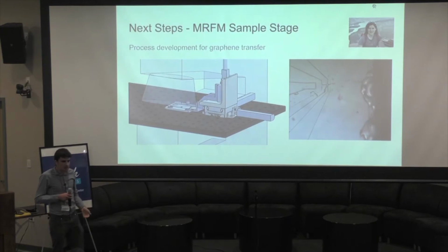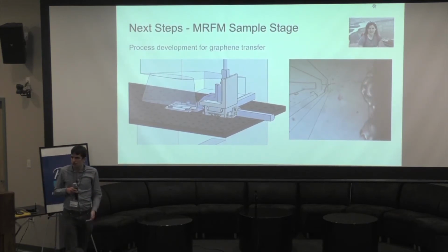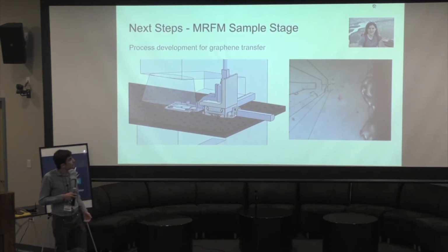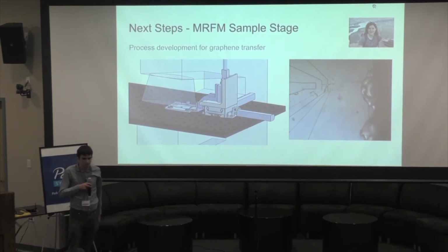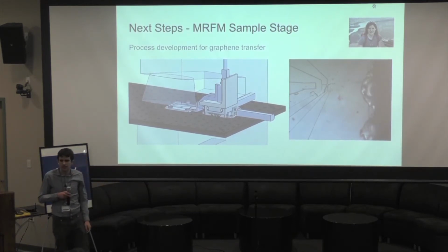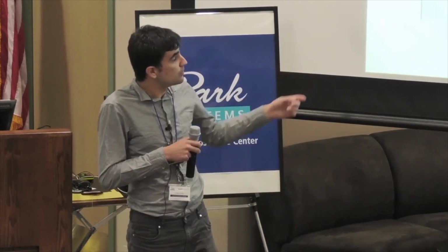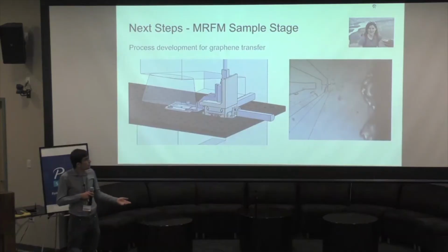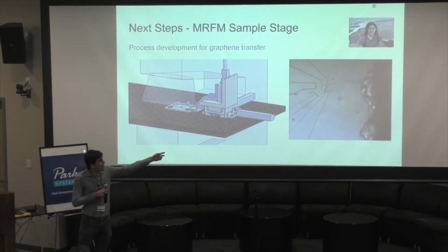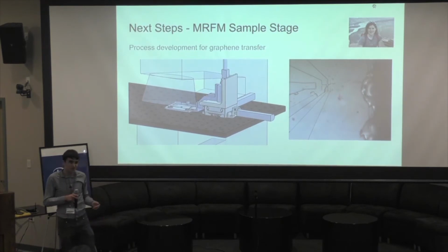The other thing that we've been doing is working on the technology development for building a practical MRFM sample stage from suspended graphene. This is in collaboration with Laurel Anderson and the Kim group at Harvard Physics. Because ultimately, if you're to make a practical sample stage, it needs to incorporate radio frequency strip lines. So you're going to have to make it via some top-down technique. So we're working on building a transfer station for building up structures from 2D materials, and also attempting preliminary transfers. You can see right there the graphene all curled up over where we're trying to suspend it. So there's still a lot of learning to do.